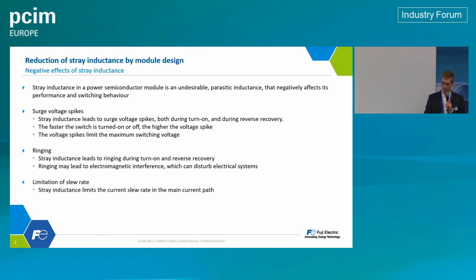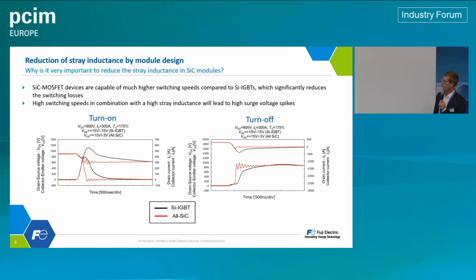So let us quickly check why it is so important to reduce the stray inductance of silicon carbide modules. The silicon carbide MOSFETs are quite fast in switching capabilities, much faster compared to the silicon IGBTs. And due to this fast and hard switching, the switching losses can be decreased tremendously. The high switching speeds in combination with a high stray inductance lead to high surge voltage spikes, which negatively affect the lifetime of the module.